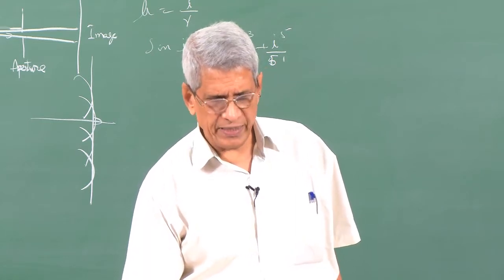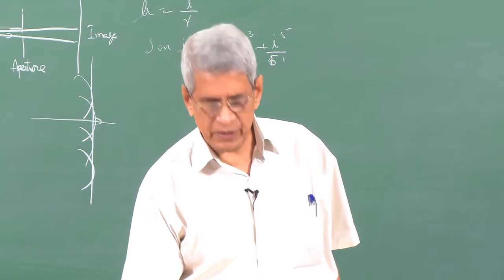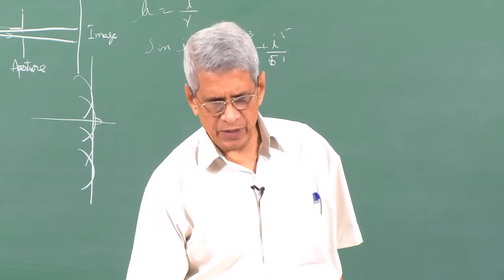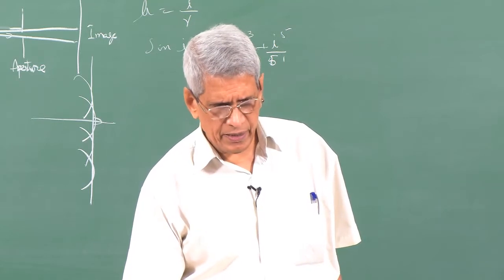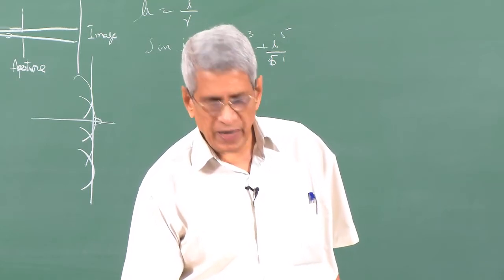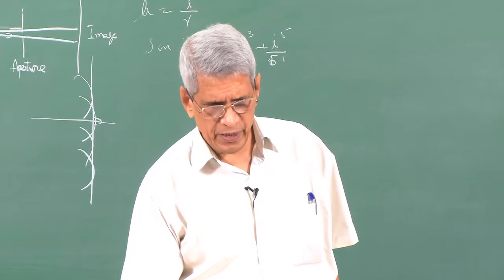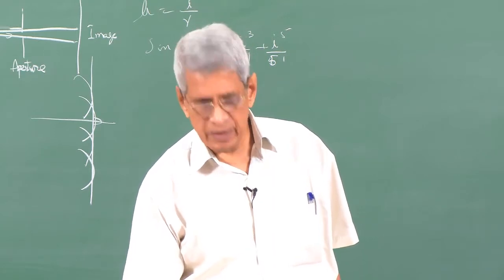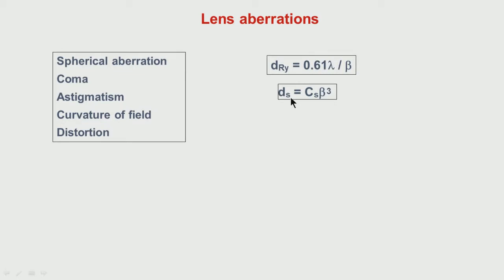As far as the Rayleigh criterion, we have looked at it. If you know the wavelength of the radiation and the angle which the beam subtends with the lens, the size of the Airy disk turns out to be 0.61 lambda by beta. Spherical aberration, for a point object, gives Cs beta cubed, where Cs is the spherical aberration coefficient. What does chromatic aberration do? It is beta times delta F, which is the defocus it creates.